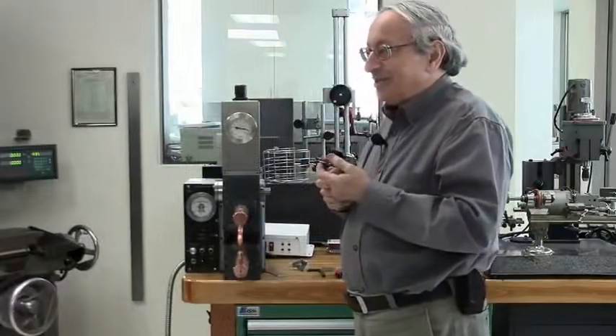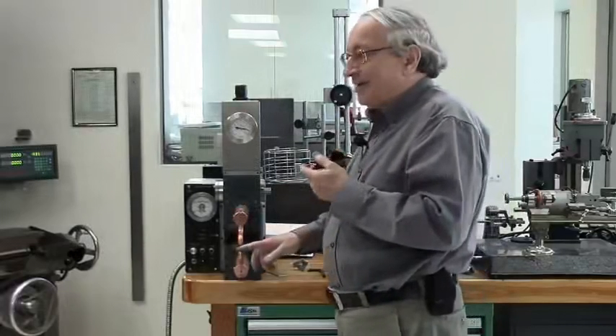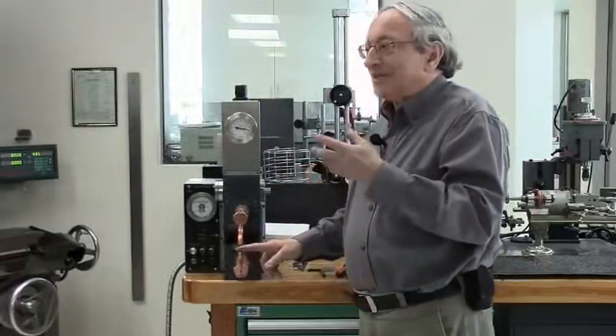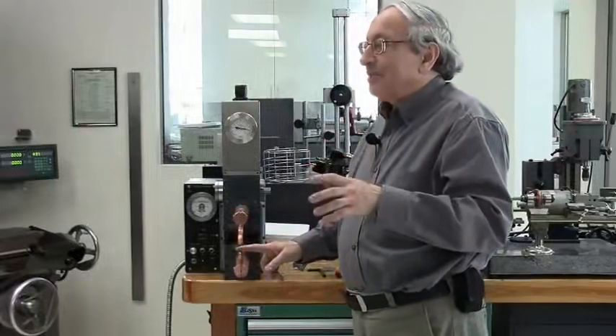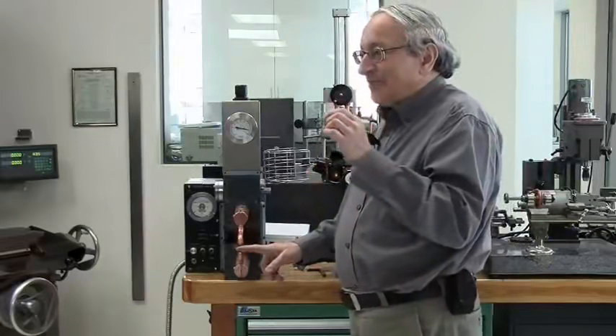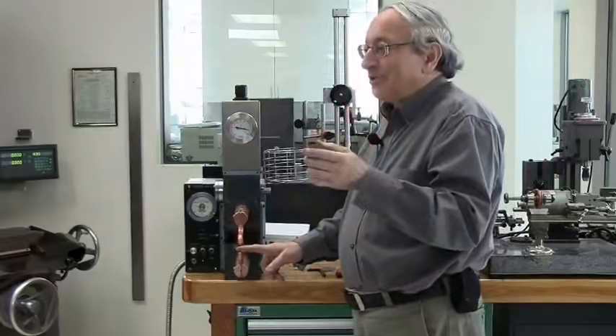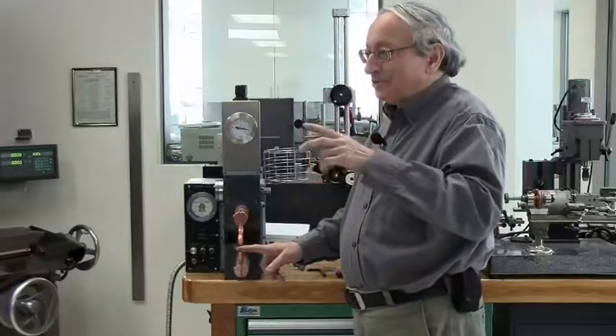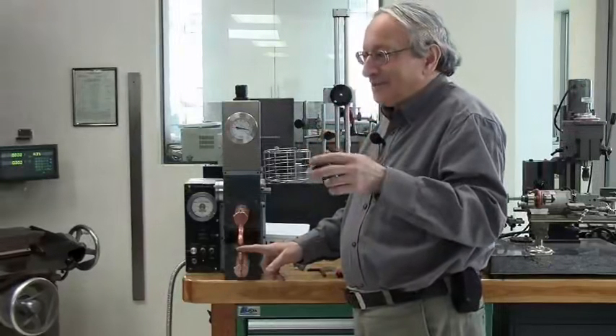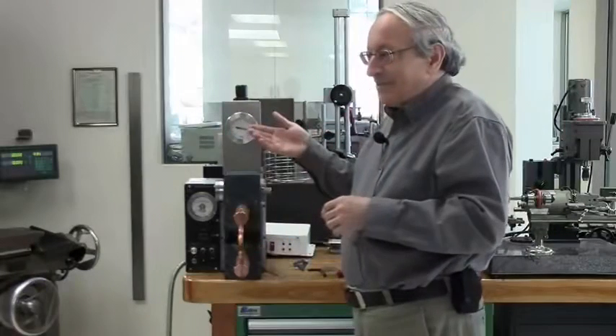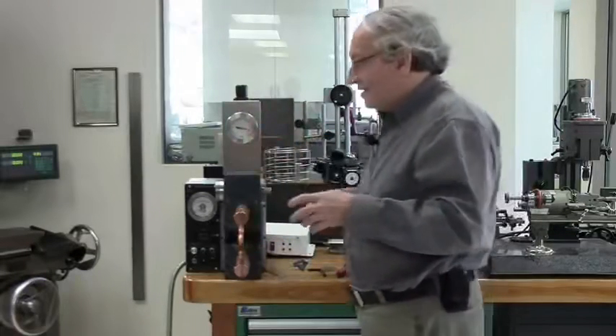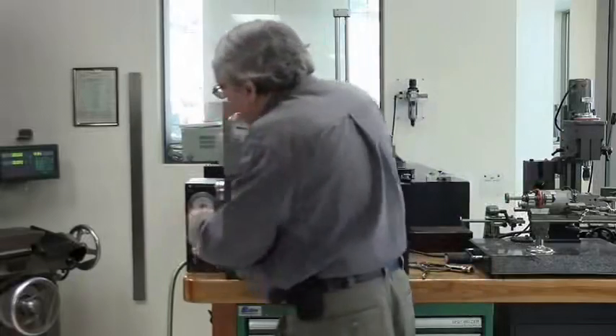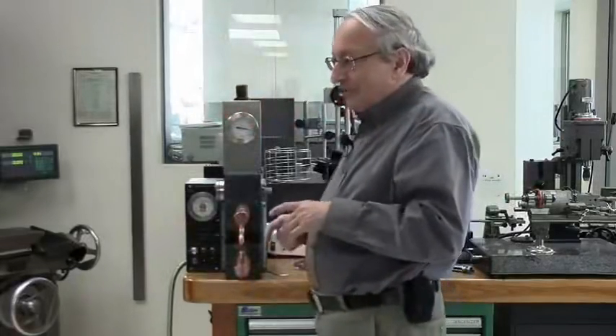So what you want is to minimize the time, so that you maximize the current and just play with the time. But sometimes for very thin stuff, one cycle is already too long, or 1 cycle, 2 cycles is too crude. You want 1.5 cycles, so you go 2 cycles with less current. But this has adjustable current. I built this 40 years ago. I never used it once.